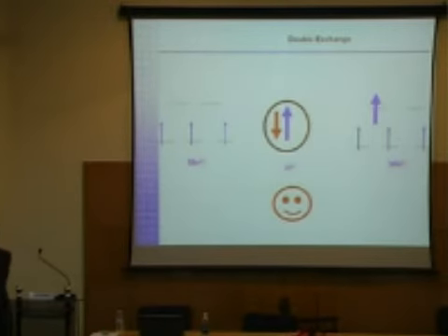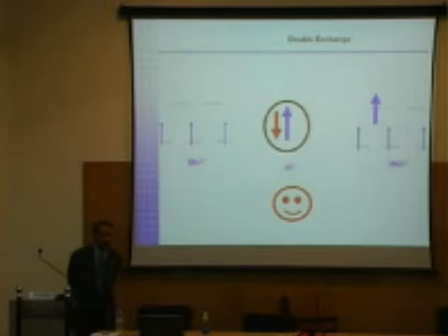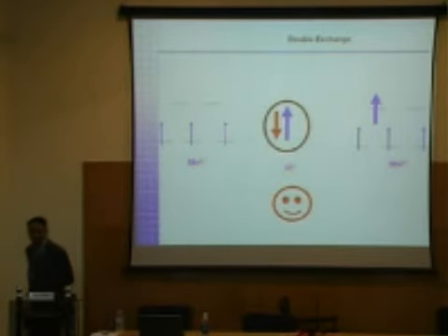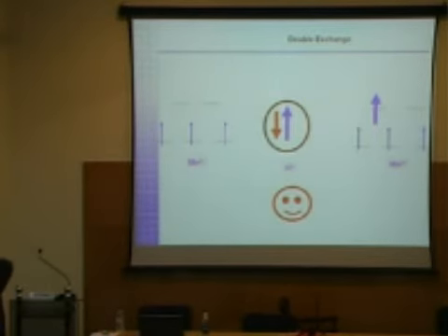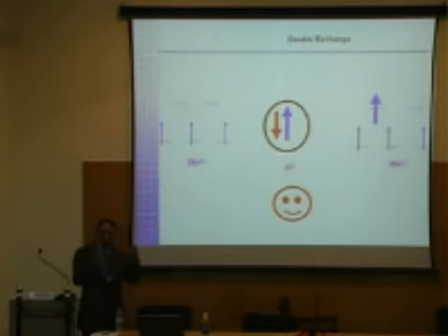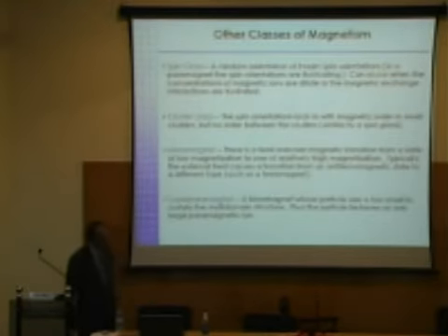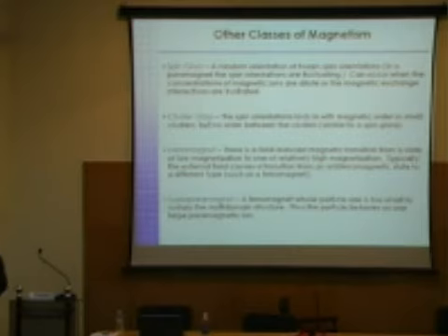In computing applications for data recording and retrieval, you need this technology. So you need materials that have superior magnetoresistive characteristics. And generally, compounds with manganese 3+ and 4+ have nearly 100% efficiency compared to the cobalt nickel multilayers that are used today. Although there are some small problems technologically we need to overcome, this is again a fundamental knowledge of chemistry that helps us design materials for advanced applications. And our group has published quite a lot of work on these things. In addition to paramagnetism, antiferromagnetism, and ferromagnetism, we also have different types of magnetic materials called spin glasses.